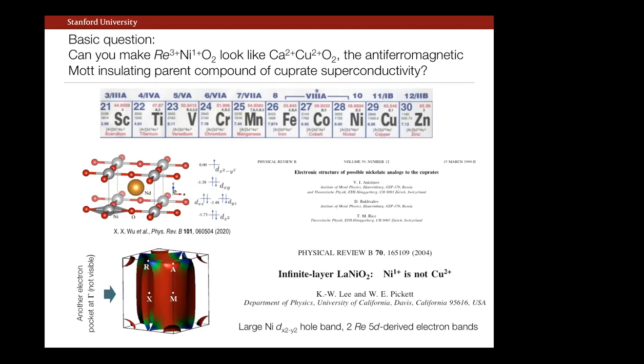Indeed, I believe this idea was kicking around even before this, but the first two papers that I'm aware of where people explicitly thought about this analogy were from this work in 1999, Anisimov, Bukhvalov, and Rice, and others, and then 5 years later by the group of Warren Pickett at UC Davis. These are both electronic structure calculations, but they were basically starting to think about this process. And you can see the interest, right? Possible nickelate analogs to the cuprates, but in Warren's paper emphasizing that actually there are key differences between nickel 1+ and copper 2+.